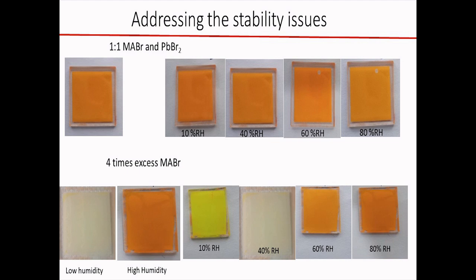This is because the methyl ammonium bromide is reacting with the water. But when we take excess methyl ammonium bromide, the film at 80% RH is more or less similar to the case of the 3-dimensional perovskite that is actually forming. So that means there is some reaction going on with the water, or some transformation taking place.